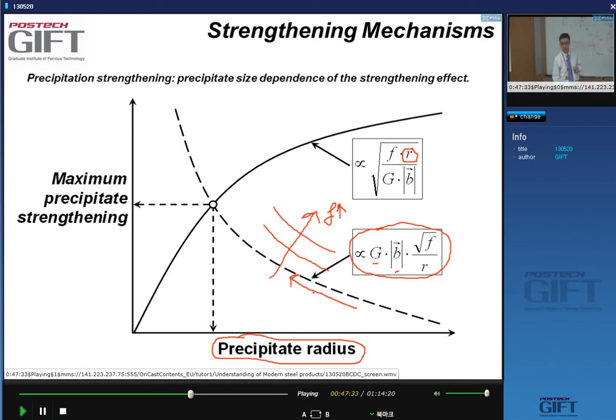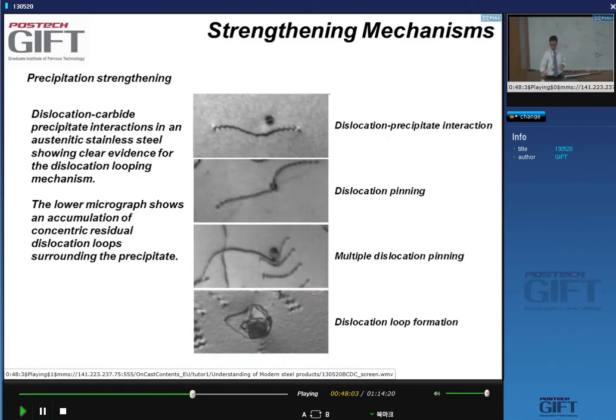Because the particle strengthening that we're dealing with is due to the presence of very hard carbides, with very different lattice parameters than the surrounding ferrite, and on top of that, very different elastic properties. So the dislocation in the ferrite, or in the austenite, cannot pass these particles. They are impenetrable obstacles. So this is an example here, where you see a dislocation and here a carbide precipitate. You see some interaction here. The dislocation here is pinned.